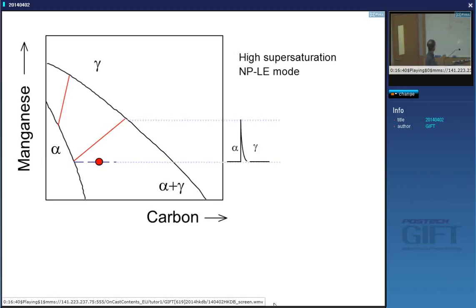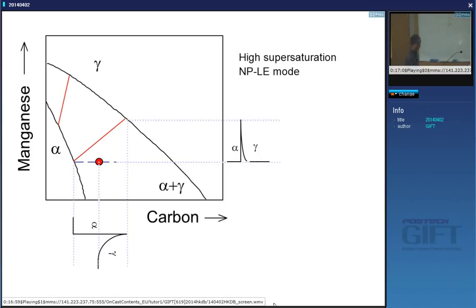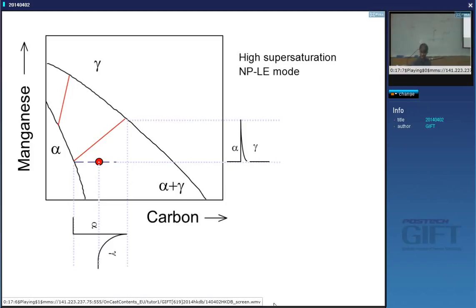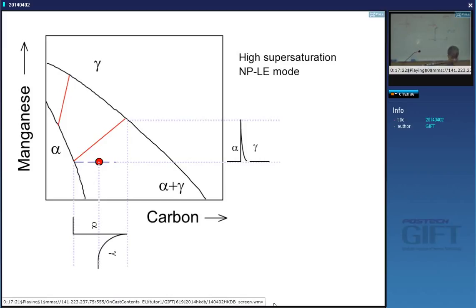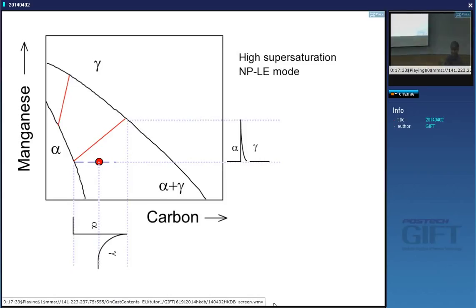If I plot the manganese concentration profile, it will be very steep, and for carbon we have partitioning over a longer distance. The ferrite has more or less the same manganese composition as the alloy. We are maintaining local equilibrium because this composition is defined by the tie line. Because the composition of the ferrite is almost the same as the austenite with respect to manganese, we call this negligible partitioning local equilibrium — negligible partitioning, local equilibrium mode of transformation. With these two methods, you can maintain local equilibrium and the fluxes of carbon and manganese can keep pace with the movement of the interface.